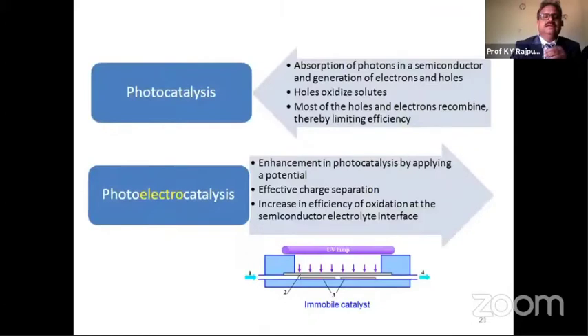And therefore, another strategy called photoelectrocatalysis. So mobile catalysis is replaced by immobile catalysis, where the photocatalyst is not moving in the polluted water, but it is deposited on the substrate in thin film form. And for this immobile catalyst, there is a provision for application of a bias through an external circuit. So it is possible to enhance the photocatalysis by applying a potential, where there is effective charge separation and an increase in efficiency of the oxidation and reduction reactions at the semiconductor electrolyte interface. So immobile catalysis or photoelectrocatalysis is the thing which I am going to explain.